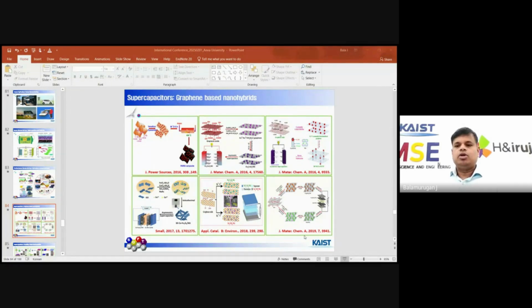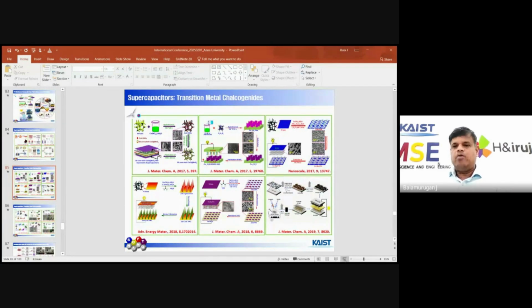Even up to 2016, 2018 or 2019, we made many types of graphene hybrid materials, but powder type materials. After fabricating the devices, we saw a problem after 10,000 cycles, so we moved from binder-based to binder free materials. When we go for binder free materials, we choose nickel foam as the substrate. Before growing the active materials on it, we have to wash the nickel foam clearly, because nickel foam usually has a nickel oxide layer. In order to remove the oxide layer, we use hydrochloric acid treatment and ethanol and water treatments.